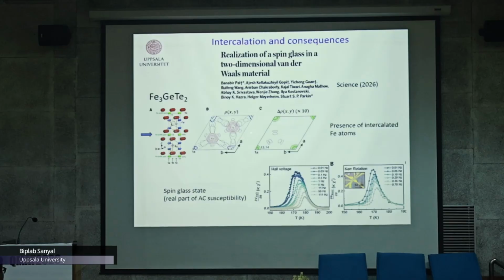Now, convincingly, they have shown some charge density difference maps, and from there they have shown that these iron atoms in the van der Waals gap sit in certain symmetry sites, and the rest of the sites are empty. So this is a two-dimensional layer in the van der Waals gap where there are dilute iron atoms. They are sitting as a binary alloy of iron and vacancies.